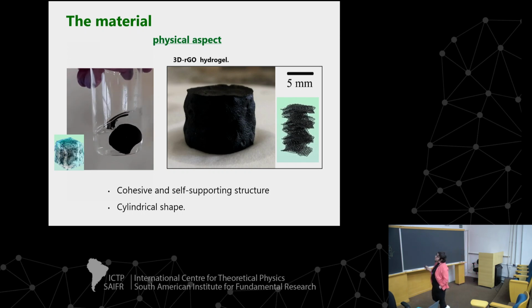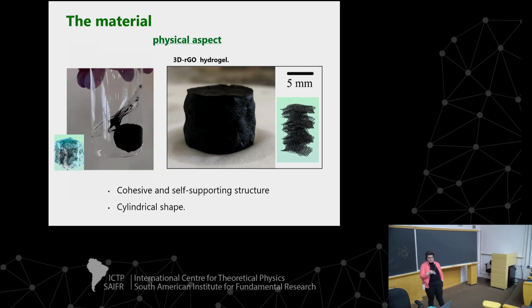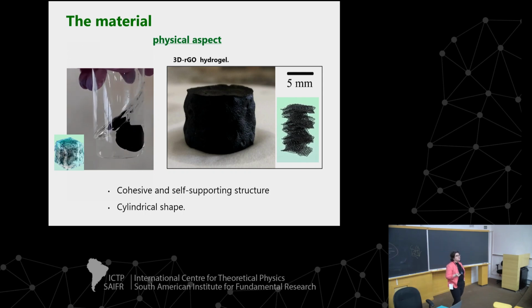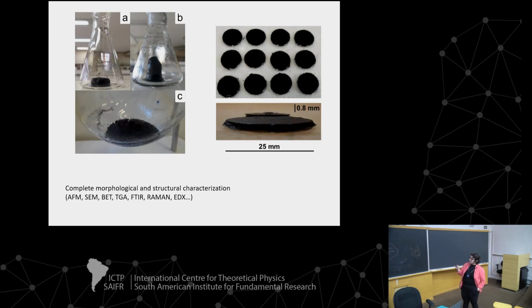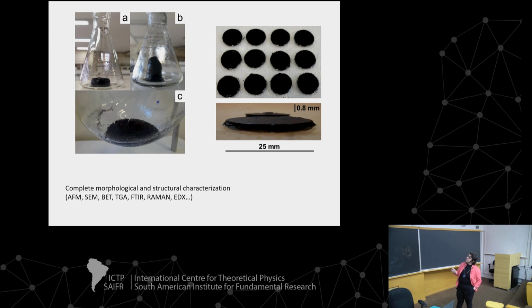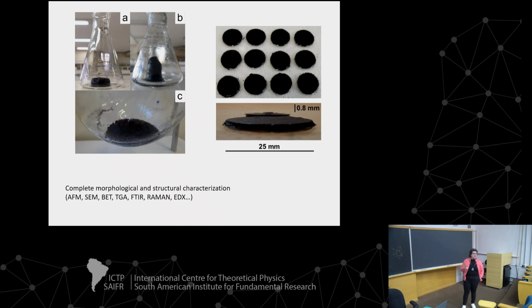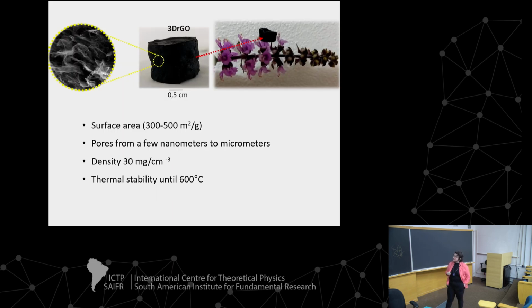This cylindrical shape is because we used a beaker during the synthesis, but we can modulate the synthesis. If I use an NMR flask, I have this kind of structure. If I have a Petri dish, we can have thin membranes like this. And we also characterize these with several experimental techniques to understand their structure, the size of pores, and the functionalization, and we have different kinds of materials.